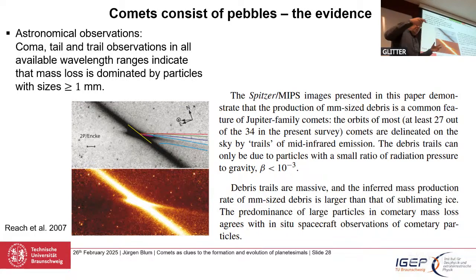So these millimeter and larger particles are ejected from the comet at extremely low speeds, just above the escape speed. And that means they stay on the orbit of the comet, but radiation pressure pushes them slowly along the orbit, because it just slows them down a little bit. It reduces gravity by this fraction. So they are slower on their orbit, they spread all over the orbit, and are identified as cometary trails. So most of the cometary trail particles are larger than a millimeter and contain most of the ejected mass.